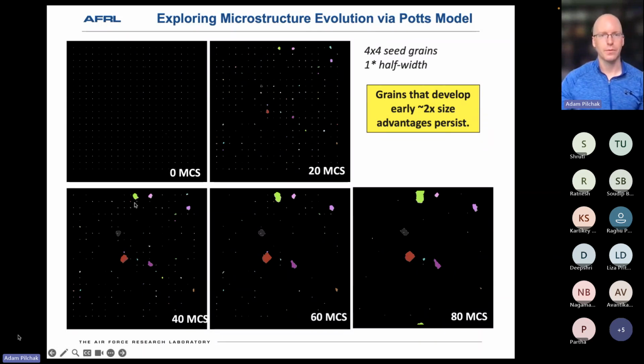So the red one, green one, for example. But another one that started to grow has also kind of shrunk in size. So this blue one, and if you go to 60 Monte Carlo steps, again, this blue one disappears. So things that initially had a size advantage and started to grow appear to also be able to be consumed by their neighborhood. So it's a complex interaction between that seed grain as well as, we determined, the first 3 shells of nearest neighbors relative to that, which I found pretty interesting.